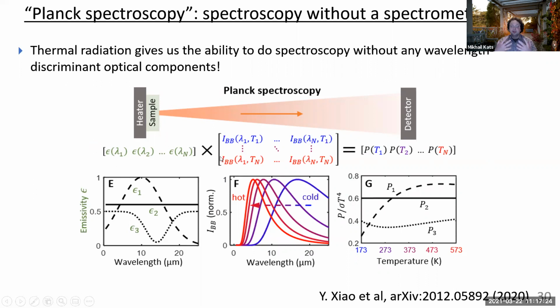And so that gives you the ability to measure a spectrum without using any grating or prism or FTIR or anything else. Now, I should say this is a very poorly conditioned problem. And it's difficult to do this inversion, and you have to use some constraints and so forth. But we were able to do that, and this is currently sitting on archive. It's not yet published, but it is in peer review. And so I wanted to show you that this, in fact, works experimentally.